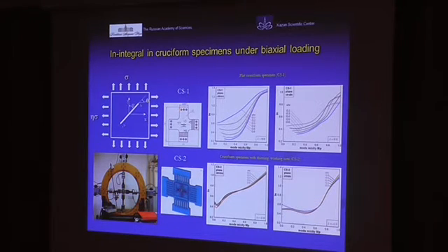For instance, for flat specimens, you see the governing parameter is a strong function of dimensionless crack length in the full range of mode mixity from pure mode 2 to pure mode 1. And the other type of biaxial loading specimen is not sensitive to this length dependence for constraint in the full range of mode mixity.